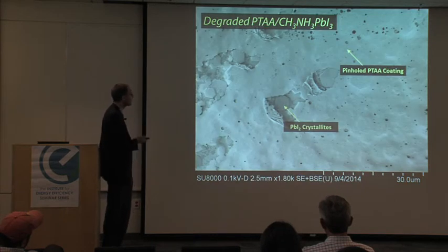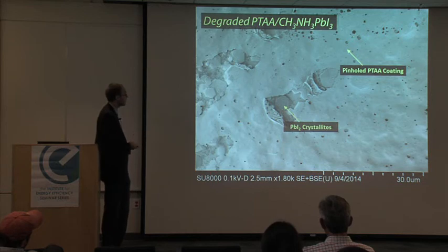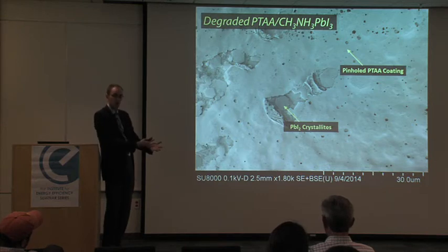Polytriarylamine is no better. You see all of these pinholes. The film looks like Swiss cheese, these big craters that are microns in size, really just allowing, again, moisture to penetrate through into the film.